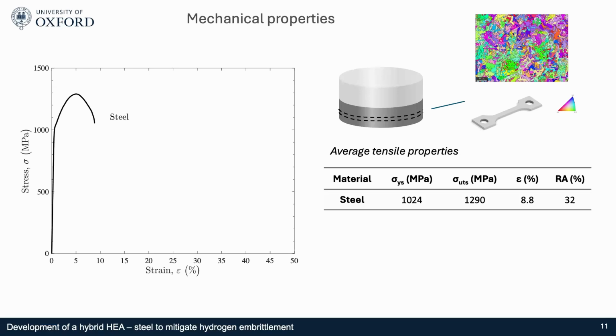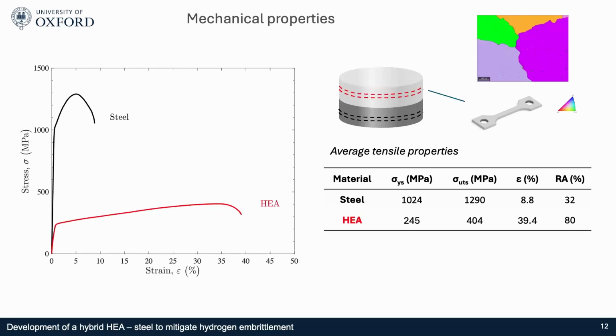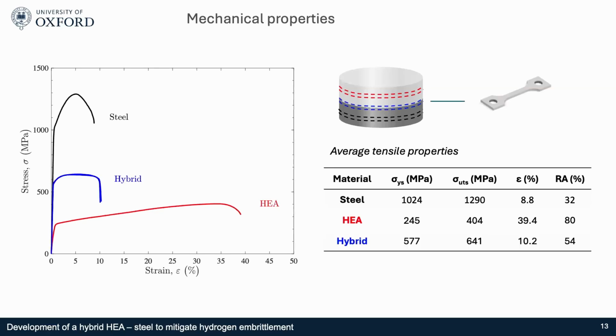For the steel, we obtained a yield strength of more or less 1,000 megapascals and an elongation of 9%. Then for the high entropy alloy, the behavior was completely different. The yield strength was 250 megapascals and an elongation of almost 40%. So for the hybrid material, we obtained the following results.